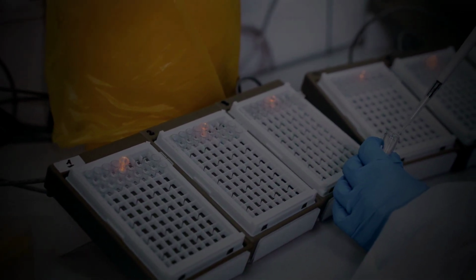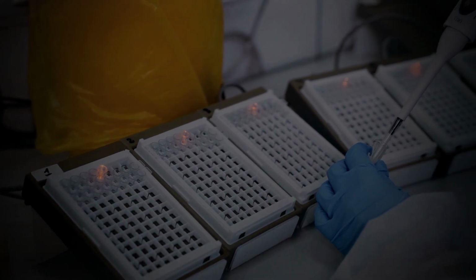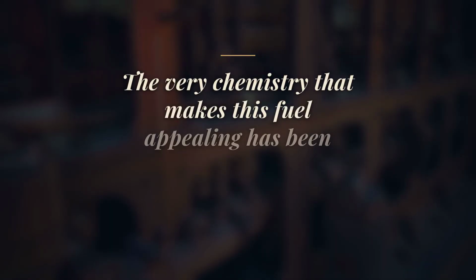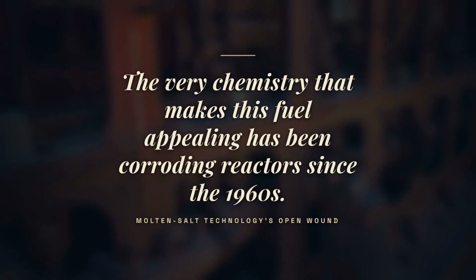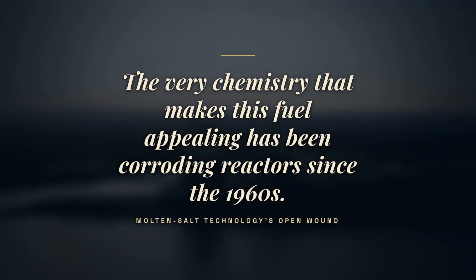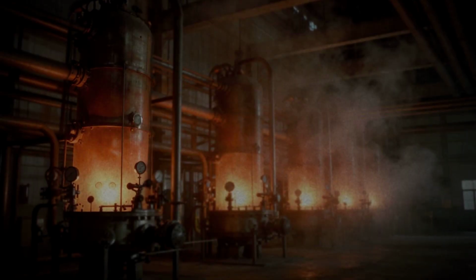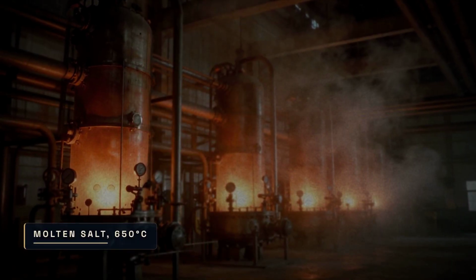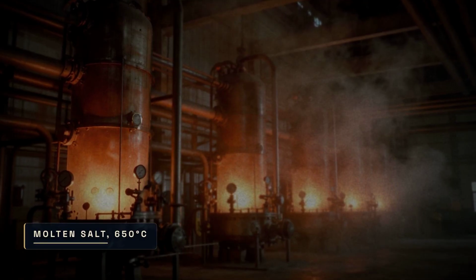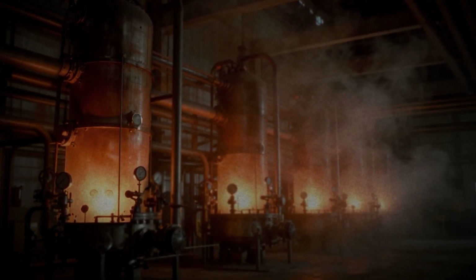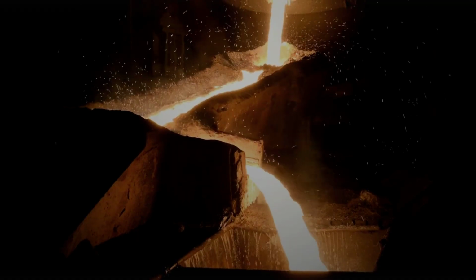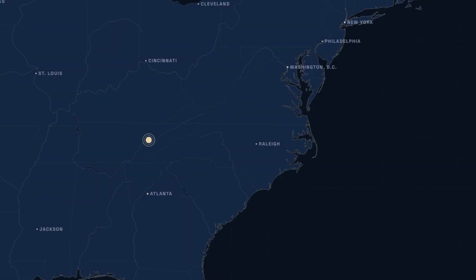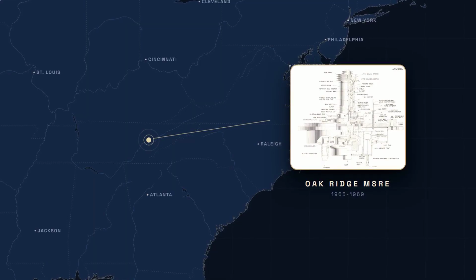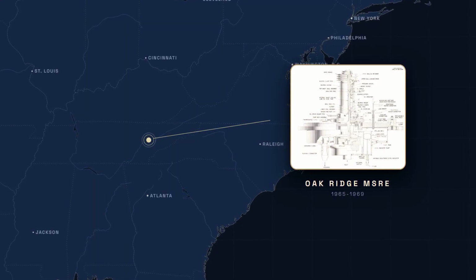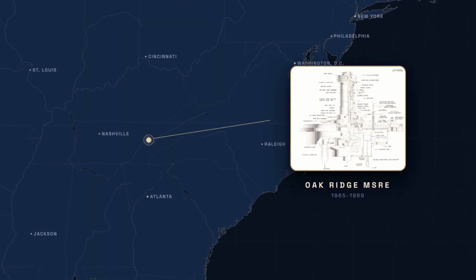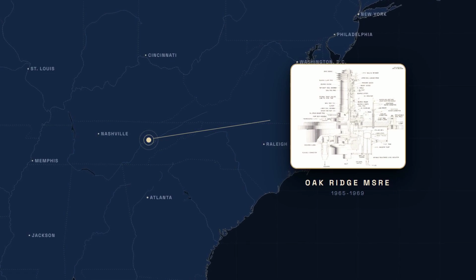The very chemistry that makes this fuel cycle appealing is also what has been quietly corroding reactor components since the 1960s. Fluoride salt at 650 degrees Celsius does not behave like a passive liquid sitting in a pipe. It behaves like a slow chemical acid, and at Oak Ridge National Laboratory between 1965 and 1969, that chemistry nearly ended the molten salt concept before it could mature.